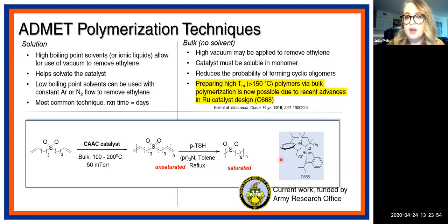Something with a melting point above about 150 degrees Celsius. This is due to recent advances in ruthenium catalyst design. So this C668 catalyst is how we're able to achieve high temperature bulk polycondensation. This is what I work on in the Wagener group right now. So I'm specifically interested in synthesizing precision polysulfones. So they'll have a structure looking like this. And we do these under, like I said, absolutely no solvent, at temperatures up to 200 degrees Celsius and very high vacuum. And then we go on to saturate to get this saturated aliphatic polysulfone.